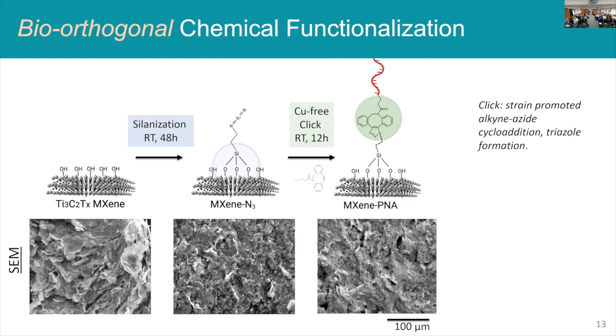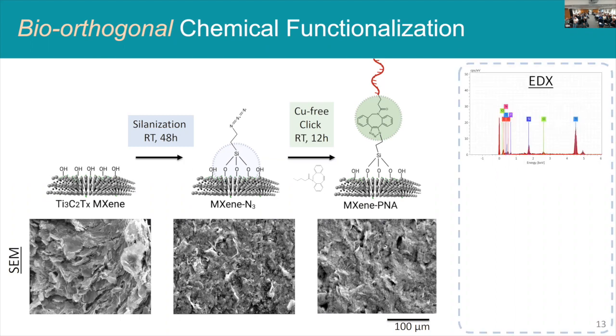With SEM, because I'm in the materials science program, of course we want to do all of the materials characterization. This is technically a completely new hybrid material that we created. So we looked at EDX, and I know this is not a materials group, but this is just showing that we have the elements that we expect. You'll see titanium peaks, carbon peaks, because that's the bare material, but you also see silicon here in blue. And you see nitrogen here showing that, yes, we've got the silanization reaction.